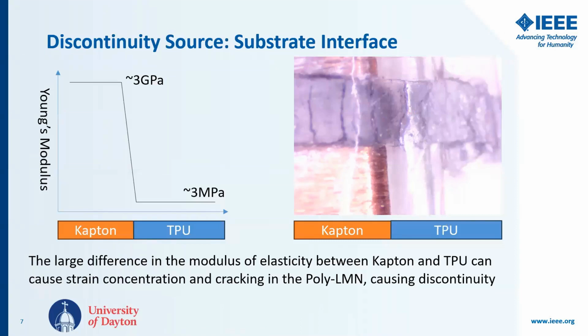However, this isn't a magic bullet. There are, again, some issues going from soft TPU to Kapton. There is a large difference in the modulus of elasticity between Kapton and TPU. TPU has a modulus of elasticity of around 3 megapascals, where Kapton has a modulus of elasticity of around 3 gigapascals.